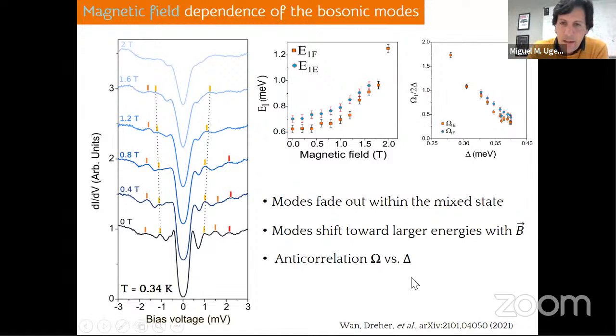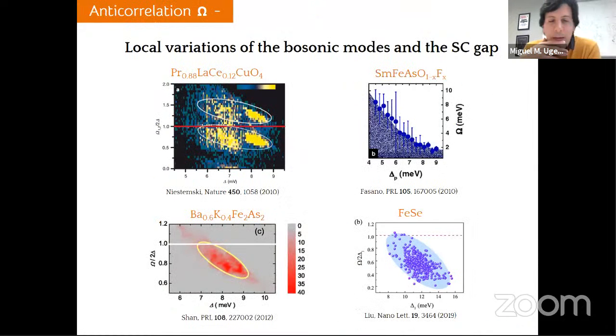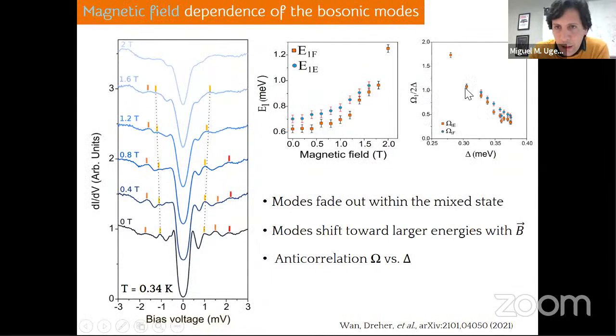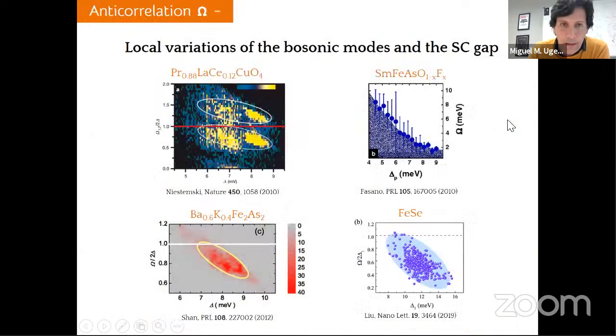Okay, so this clear anticorrelation is something that has been observed in the past for spin excitations, or spin resonances, I'm sorry, in many different unconventional superconductors. Here I show you 4 of them using tunneling spectroscopy. You see that in all cases, basically the omega, the energy of this fundamental mode, decreases as we increase the size of the superconducting gap. But in all these cases, this has been proven by studying local variations of the bosonic modes, not using the magnetic field, as I show you here. Here I show how this is anticorrelated using the magnetic field.